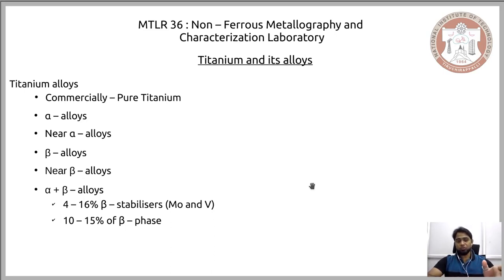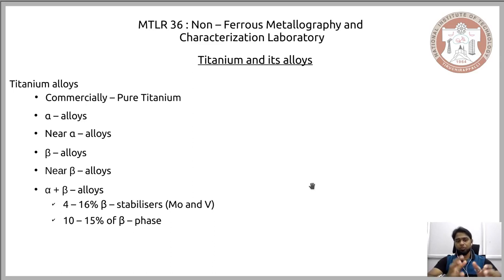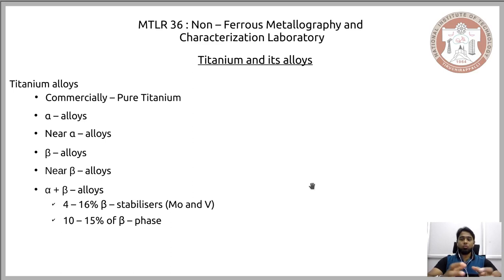Finally, we have alpha-beta alloys — a definite combination of alpha and beta phases, not corresponding to near alpha or near beta. This alloy is achieved with a range of 4 to 16 percent beta stabilizers, resulting in 10 to 15 percent beta phase at room temperature. Rather than having a designated nomenclature, these categories — based on the allotropic alpha and beta forms — define the titanium alloy system. The dominant phase at room temperature indicates which alloying elements are present.